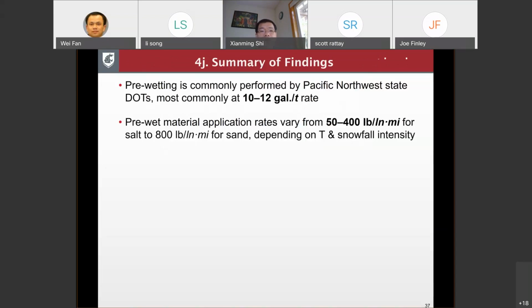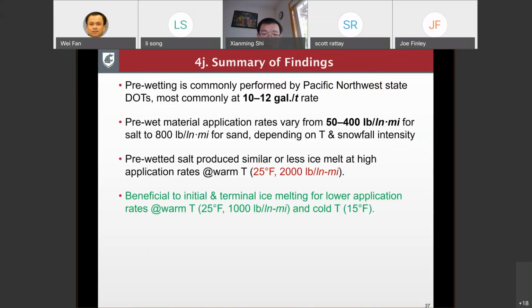So to summarize, pre-wetting is commonly performed by Pacific Northwest state DOTs, most commonly at a 10 to 12 gallons per ton rate. And pre-wet material application rates vary from 50 to 400 pounds per lane mile for salt, and up to 800 pounds per lane mile for sand, depending on pavement temperature and snowfall intensity. And pre-wet salt produces similar or less ice melt at higher application rates at warm temperature, but the pre-wetting is beneficial to initial and terminal ice melting for lower application rates at warm temperature like 25 degrees, 1,000 pounds per lane mile, and cold temperature.